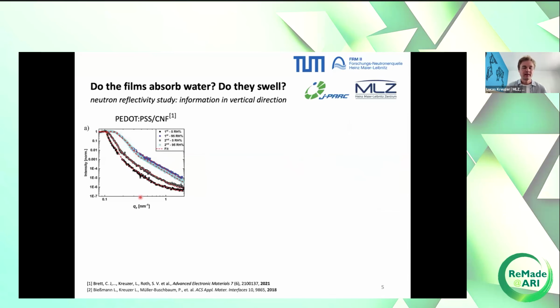Now, these are the reflectivity curves of our material, of the PEDOT:PSS CNF films. Intensity is a function of Qz. They do not look so nice as the simulated curves on the last slide. Real science rarely does, but we can analyze them.